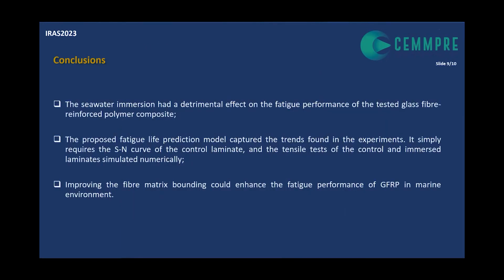To conclude, the seawater immersion had in fact a detrimental effect on fatigue performance of the composite tested. The proposed fatigue life prediction model captured the trends found in the experiments, and it simply requires the SN curve of the control sample and the tensile tests of the control sample or immersed sample, which can be simulated numerically. Lastly, by improving the fiber and matrix bonding, we could enhance the fatigue performance of glass fiber reinforced polymers in marine environments.